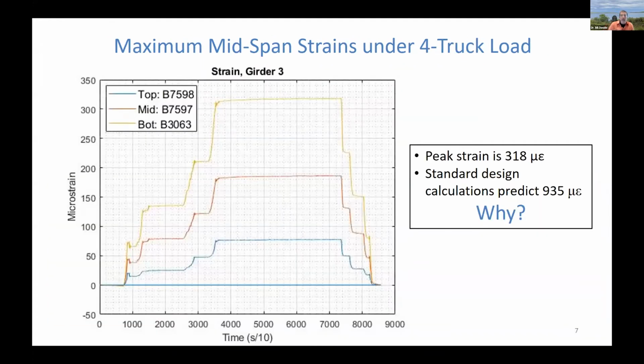So here are some typical results. These are the largest strains that we measured in the central girder, and that's the most heavily loaded girder. Girder 3 is the third of 5, the one right in the middle, under a 4-truck load. And one thing jumps out at us right away. We have 3 gauges over the depth of the section, one near the bottom, one at the middle with a red line, and one near the top of the beam. And we see that all of these strains are tensile. We're peaking at about 320 or so microstrains, significant strains in the middle, also significant tensile strains at the top of the girder.